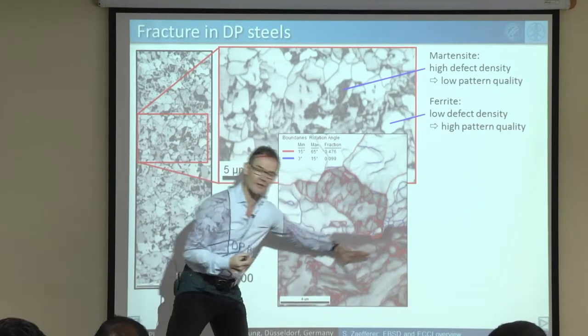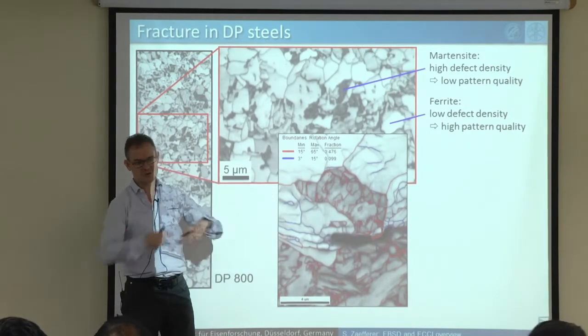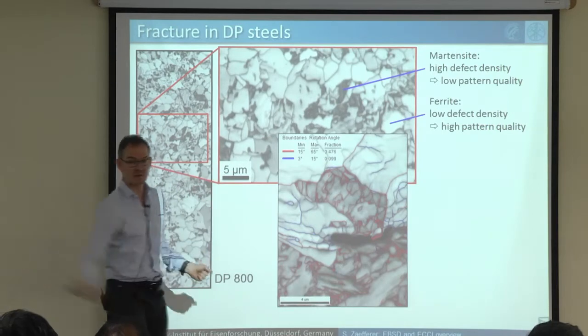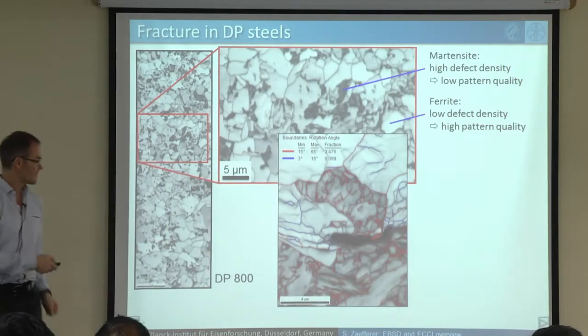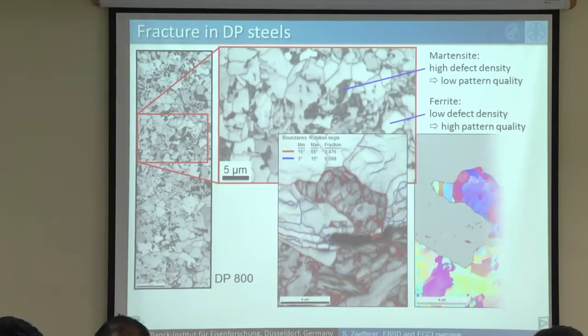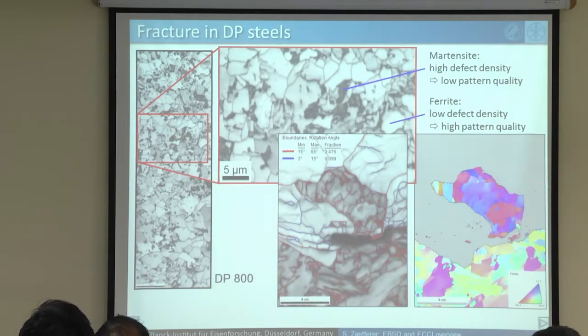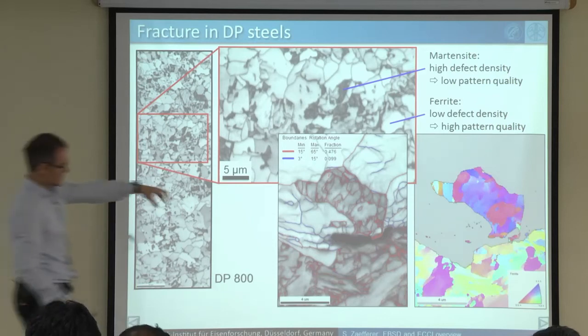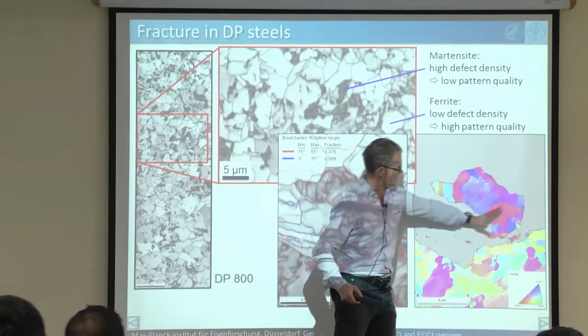But if we would understand better where the cracks form and why they form, we could make perhaps a DP steel much better, much more fracture resistant. So we looked into the martensite. This is the martensite here. I just don't show the ferrite which is around here. And you see again all the martensite lamella in here.